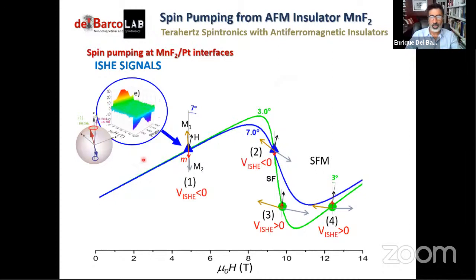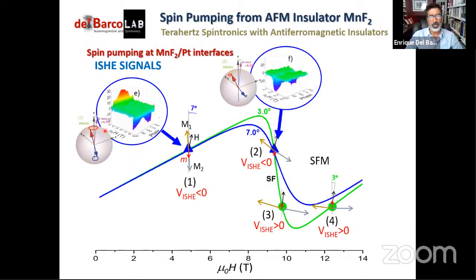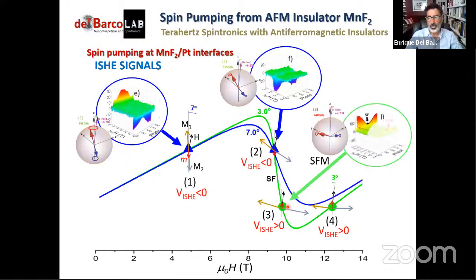Then we keep going, we go to the spin flop transition. Now we see something that is basically similar, right, in nature and similar in behavior. We keep going down, and now we are in a different thing, right? So we still have some kind of, you know, memory of the circular polarization, the mode is still circularly polarized. But now we're far from being aligned with the c axis. And so we have some features, as we have before, like the same modulation as a function of the phase of polarization of the microwaves, but the signal is actually totally reversed. And if we go to the quasi-ferromagnetic mode, look at what happens here. Now we're already having some elliptical polarization, and eventually it will become fully linear. So we don't really expect strong spin pumping out of this mode. And that is maybe why this is not modulated.